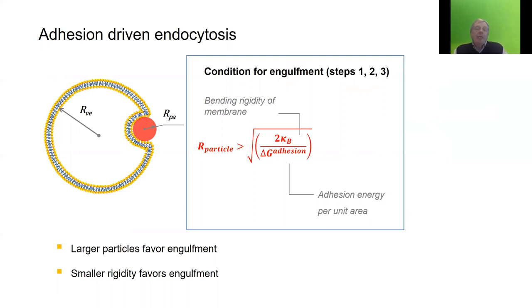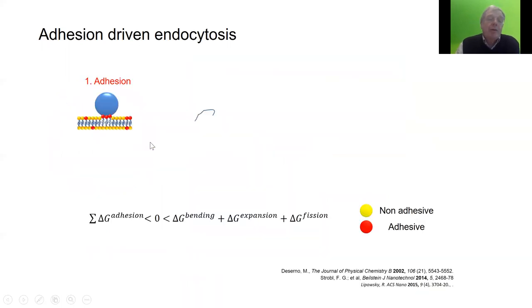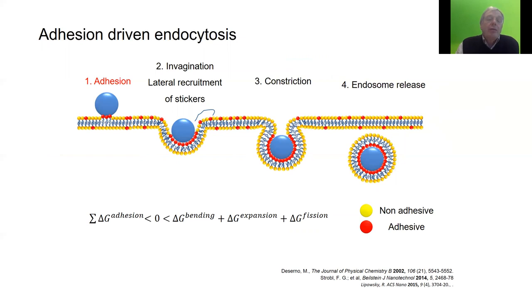Both of them can be manipulated. And if you evaluate this, you find that the larger the particle is, the less you have to bend the membrane, and the lower the adhesion energy can be in order to have the conditions for this type of engulfment. So you can use this. If you have a particle adsorbed by the membrane, and the adsorber molecules in the membrane can move laterally, they will be called together by the particle. The particle can adsorb more strongly and even more strongly, and finally it is engulfed.